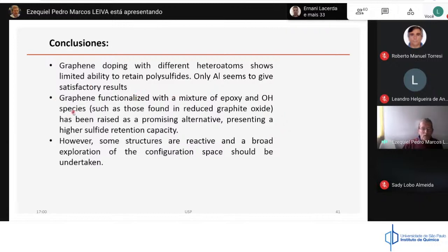This is something I did not discuss here. If you try to use reduced graphite to keep the polysulfide, you have the problem that your polysulfides react with the surface, and at the end of the day, you finish without oxygen on the surface because the polysulfide is going to take that away. This is something that we studied, but I'm not going to speak on that now. This must be further investigated, the possibility of retention of polysulfide by oxidized graphite surface.